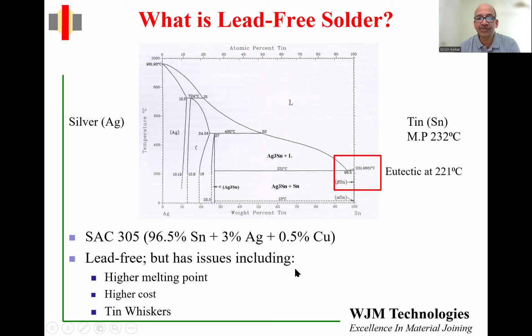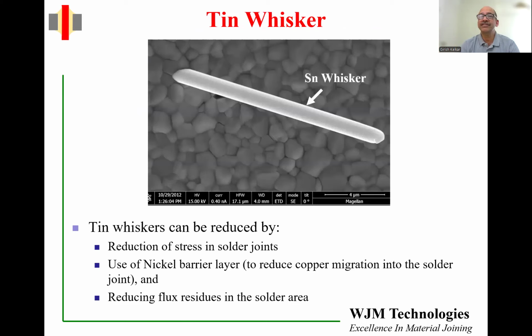However, there are some issues. First of all, the melting point of this solder is a good 20-30 degrees higher than a tin lead solder, and that produces challenges. Secondly, the cost is also greater. Now we are adding silver and we are adding a third component. As the mixture becomes more complicated, the cost also goes up. And perhaps the most detrimental is what is called tin whiskers. So what exactly is a tin whisker? Now, tin whiskers do not form in tin lead solders. So this is one of the benefits of tin lead solders: we do not have the issue of tin whiskers.